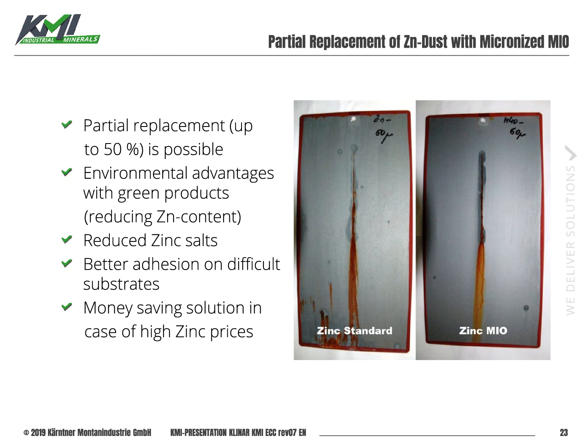Another application is the partial replacement of zinc dust in zinc-rich prime coatings. Together with the Corrosion Institute in Dresden we found out that a partial replacement of up to 50% per mass in a 1-to-1 ratio is possible. The advantages are you have environmental advantages because you can lower the zinc content of your coating. You have some technical advantages. You reduce the building of zinc salts, which has a positive influence on the intercoat adhesion. And for sure you have again the effect of better adhesion, especially on difficult to coat surfaces.